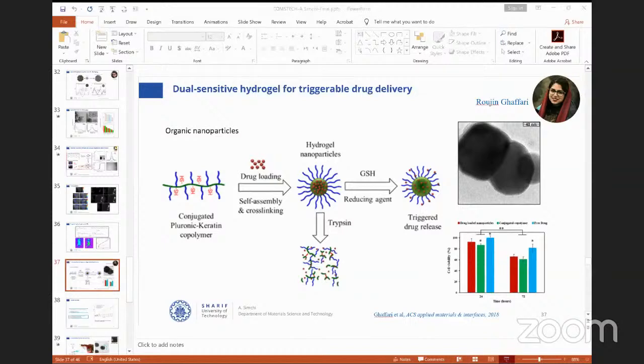The size of the nanoparticles is about 40-50 nanometers. When we inject it inside the body, trypsin or glutathione react with the surface, break the disulfide bonds, and release the biomolecules inside the cancerous cells or any target tissue. We show that the system works very nicely inside the body of a mouse.